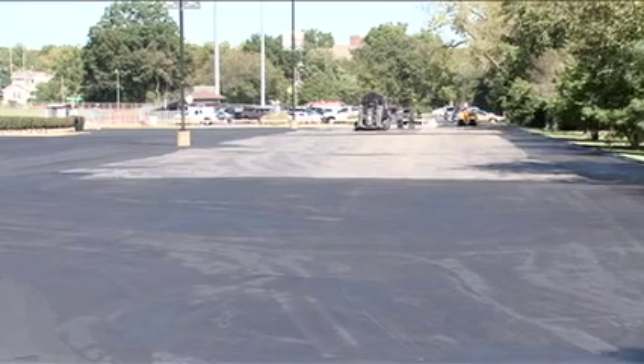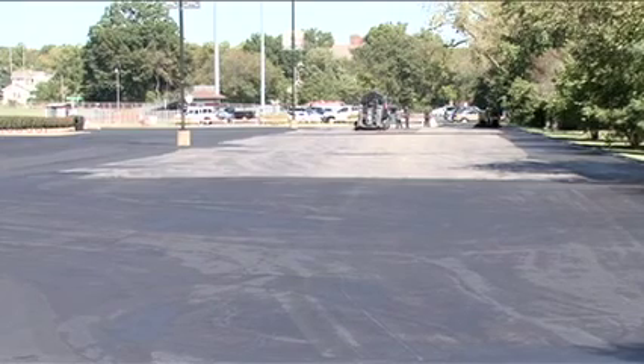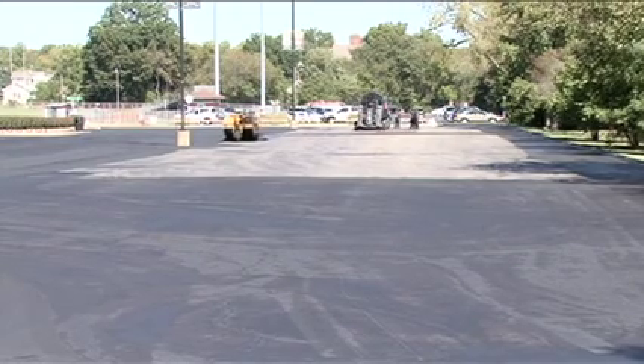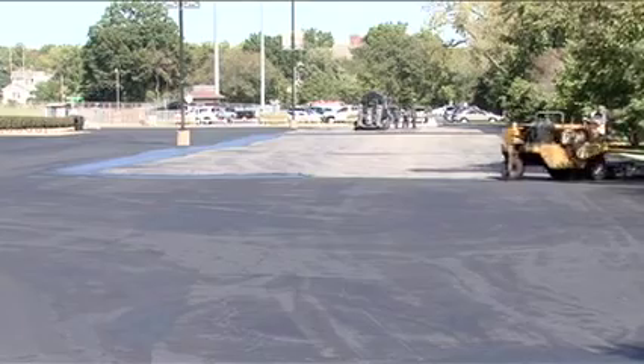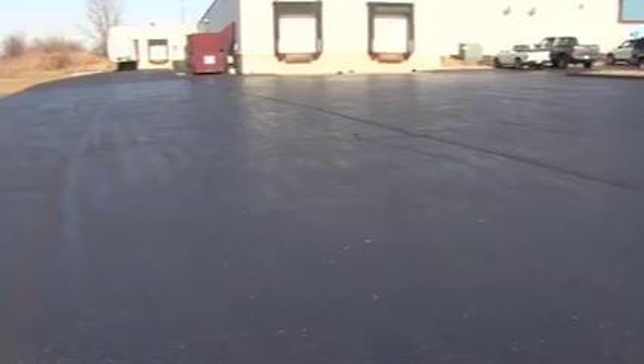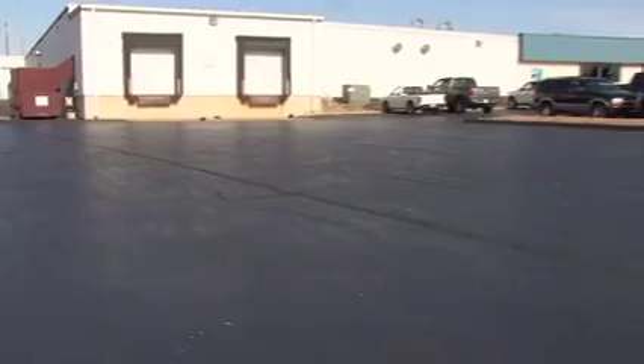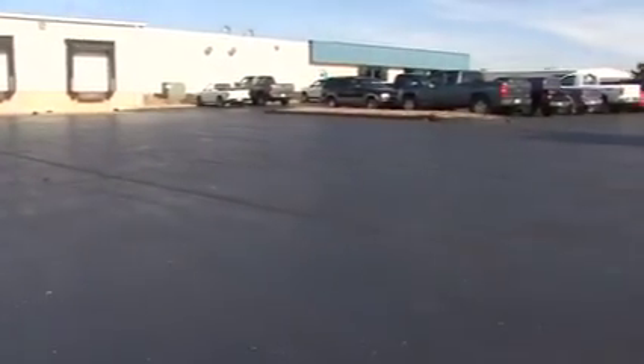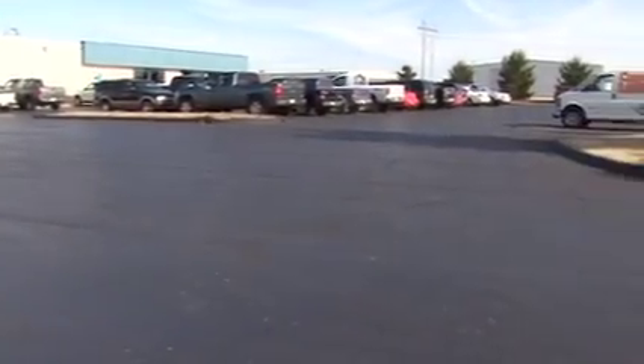And at the same time, any fuel or oil spills. You know, I tell people, if you had an asphalt parking lot, the last thing you'd want to do is take a 5-gallon pail of gasoline and go out and throw it on that surface. It would literally eat the asphalt away, causing, without question, failure. So a seal coat on top of that surface is going to protect that material from getting down into the asphalt. The refined tar-based product would keep that gasoline and let it run right across the top of the surface, where the asphalt-based emulsion seal would actually accept that gasoline, break it down, and then also go into the asphalt.